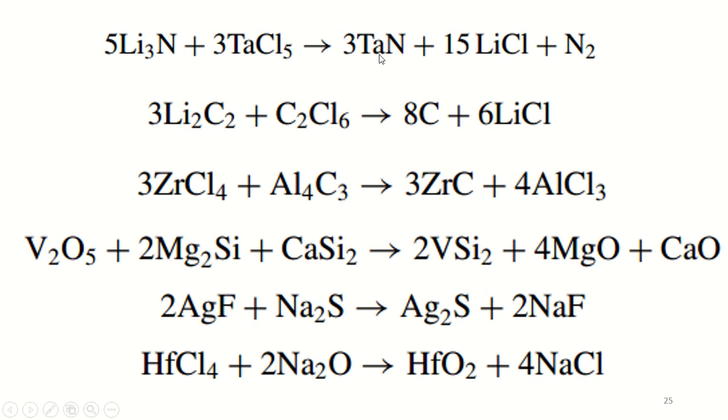SSM methods are usually better controlled than the SHS method, since the boiling or volatilization of the side products reduces the driving force for the reaction, and therefore limits the temperature attained during the synthesis to the boiling point of the side product.